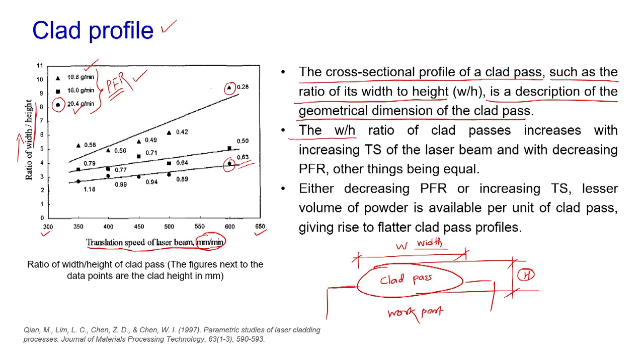So, the W by H ratio, the width to height ratio of clad passes, increases with increasing TS, while it is decreasing with PFR, when the other process parameters are constant. So, to have a higher width to height ratio, you can decrease the PFR value or you can increase the TS value. So, why is this happening?